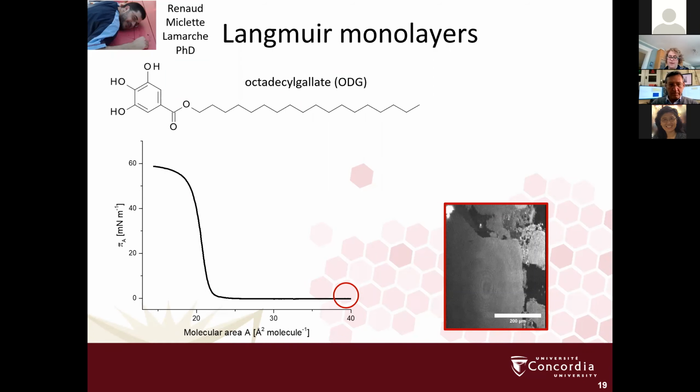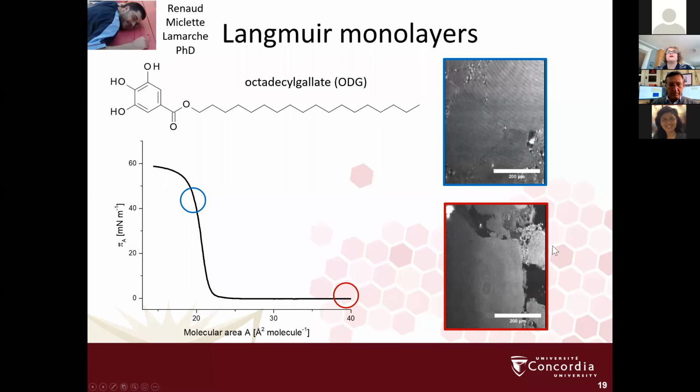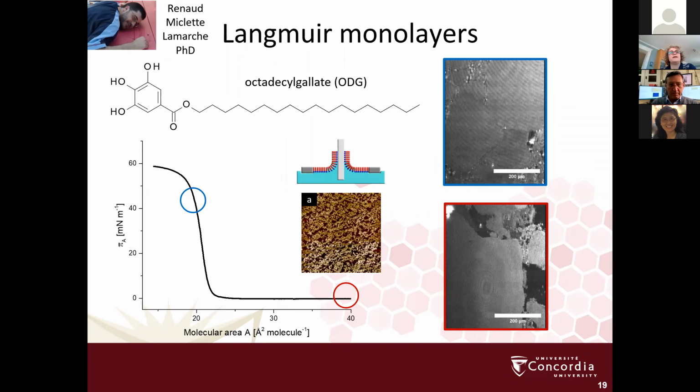Again, you get these rigid domains that are forced together. They don't coalesce nicely. You still see the residual areas. You see the collapse occurring on the grain boundaries where the domains have been compressed together. And these are so rigid that not only do they push the Wilhelmy plate out of plane, they don't transfer well. So they actually break up upon transfer onto mica.